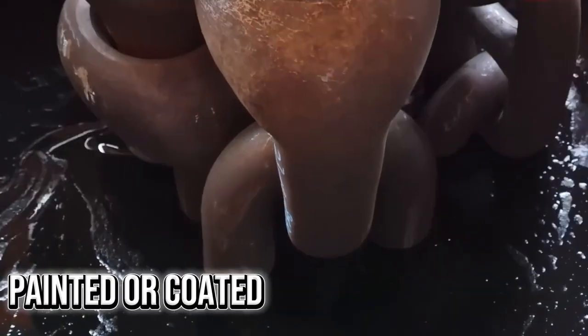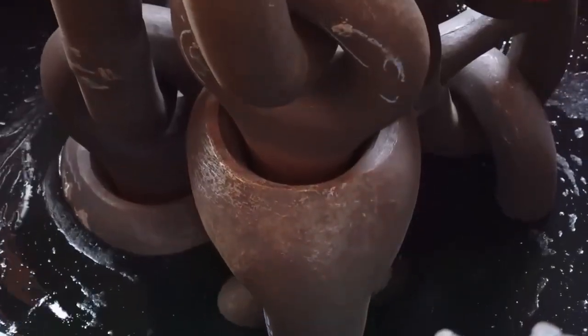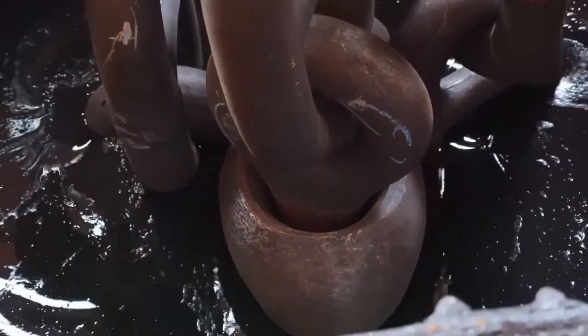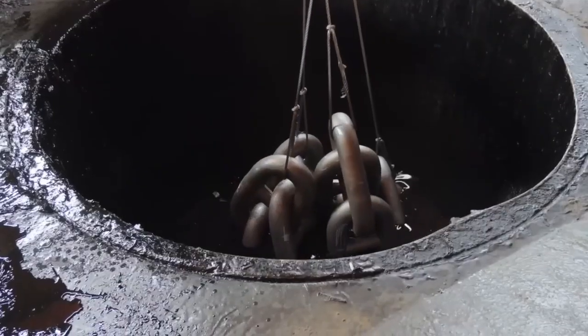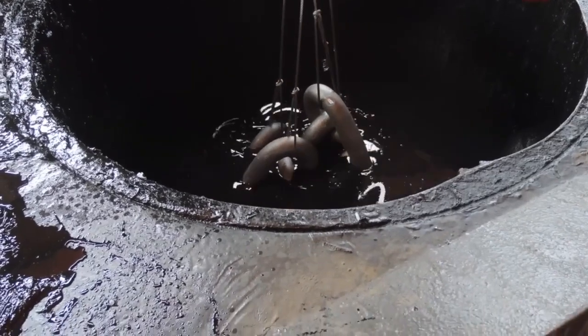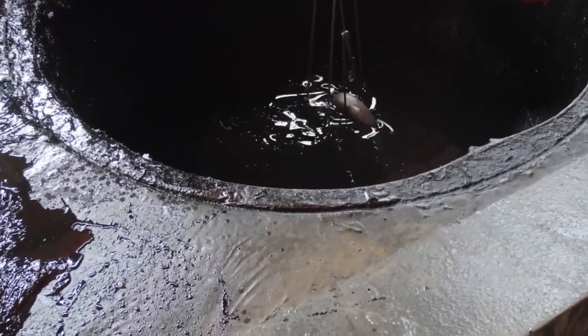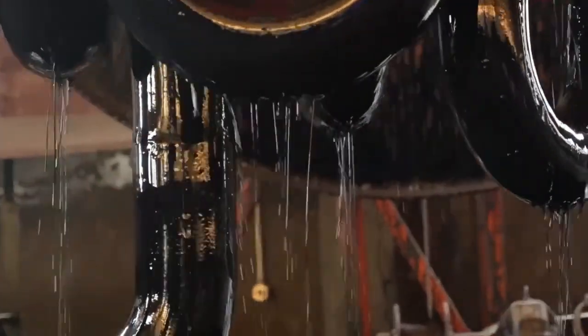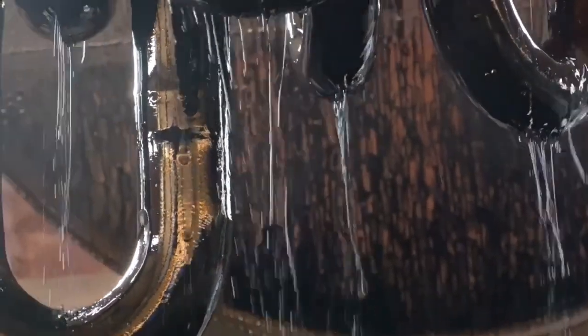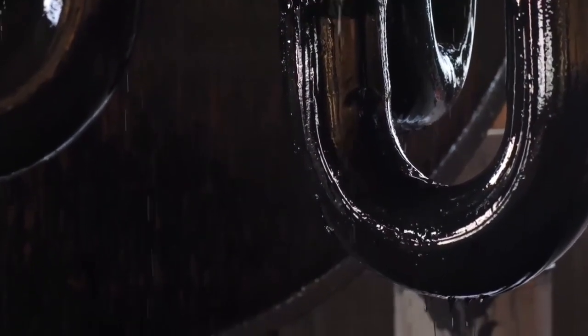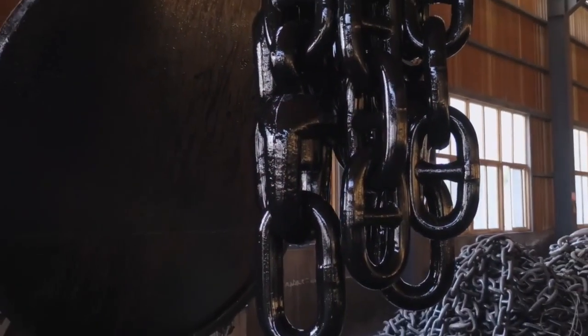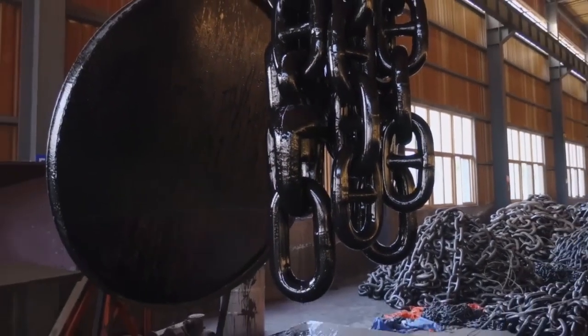Now the chain is painted or coated. Marine chains use heavy protective coatings, sometimes involving zinc-rich primers, epoxy layers, and polyurethane coatings. Saltwater is a chemical weapon. Salt penetrates microscopic cracks, forces reactions with iron, and slowly expands as corrosion grows. The coatings slow that attack. Some manufacturers use special cathodic protection systems that sacrifice zinc instead of the steel.